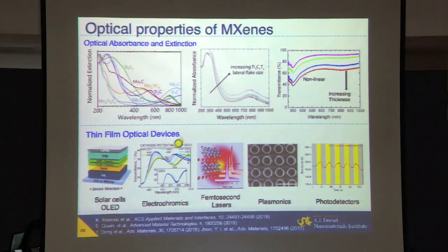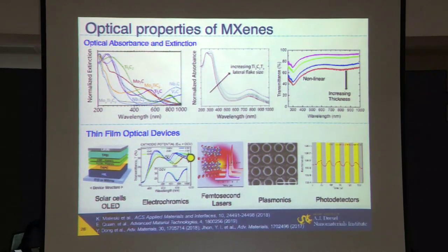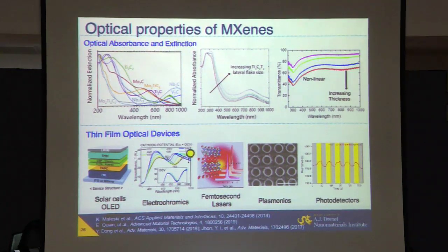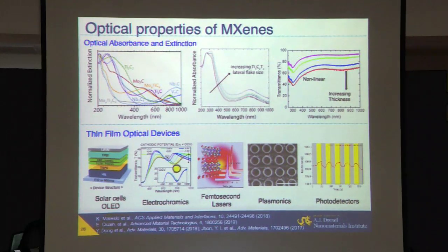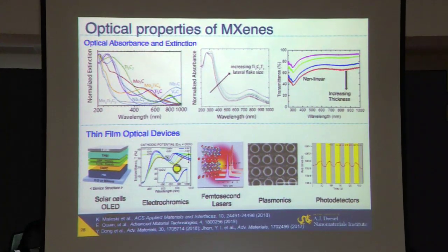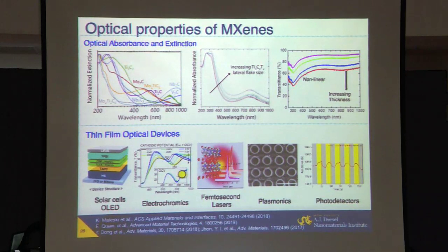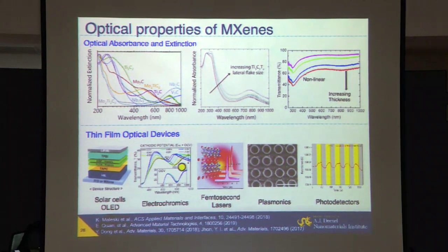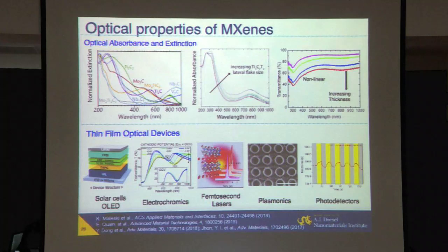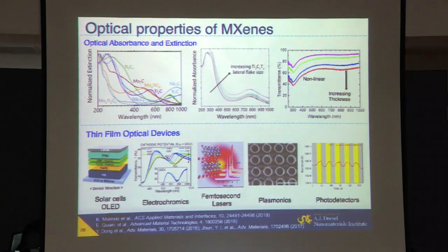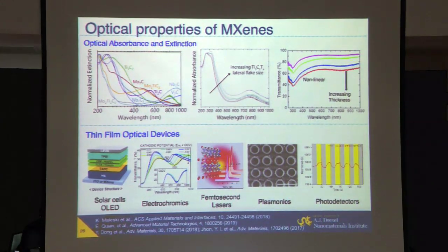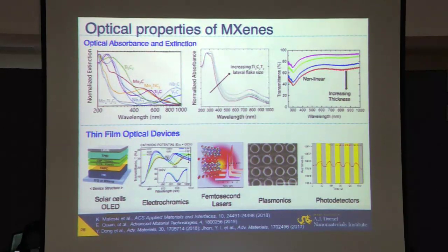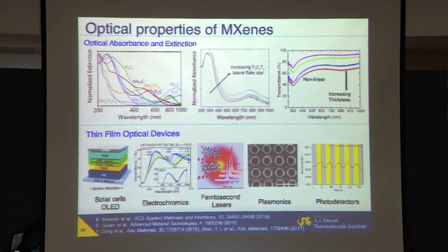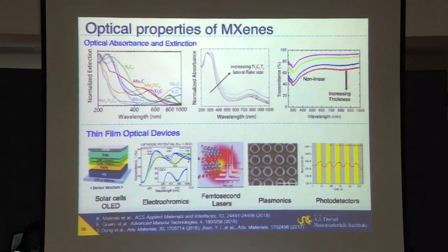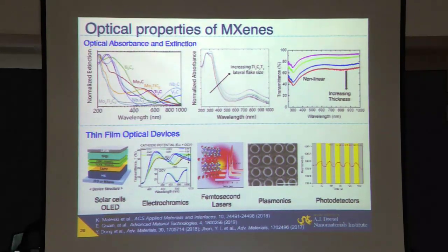And you can actually tune them by applying just 1 volt potential, negative potential, to MXene with an electrolyte between the layers. We can shift it by, in this case, it's shown 100 nanometers, so basically going from a transparent film, which would be green, to blue color, and we actually go up to 150, 160 nanometers with just 1 volt applied potential. So again, it's a very interesting metal with tunable properties, tunable optical properties, tunable electronic properties.